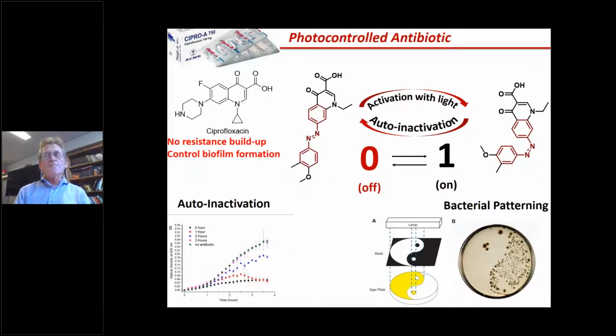And so here you see an example of an antibiotic. This is ciprofloxacin, which is a broad spectrum antibiotic. What we did is, in this structure, we take away the heterocycle, we build in an azobenzene switch, and now we can control the on and off state of the activity of such an antibiotic. So the nice thing is here, we can switch it on from the so-called trans form to the cis form. The cis form is active, and it automatically deactivates, and we can tune that precisely. So it can be off again after 3 hours, as you see in this figure here. It auto-inactivates after 3 hours, 6 hours, 24 hours.